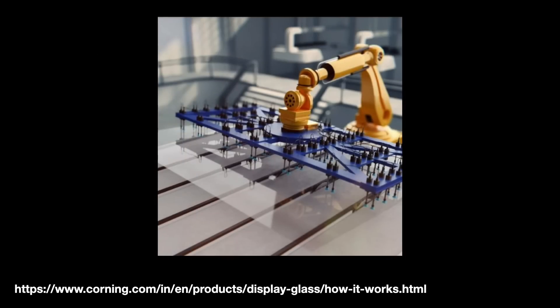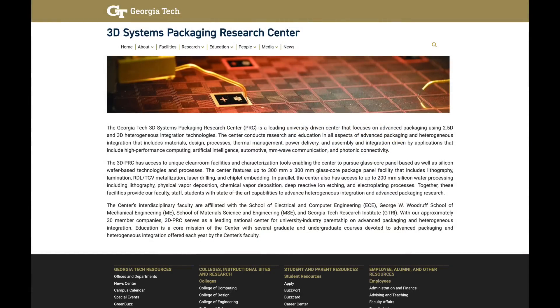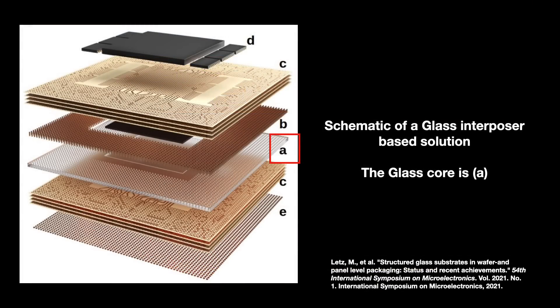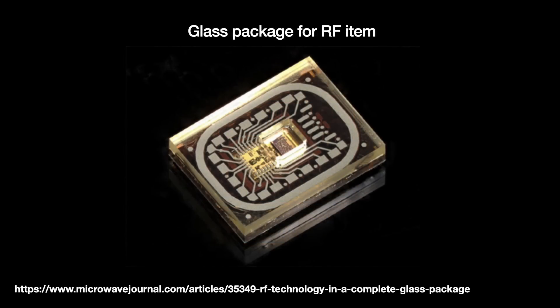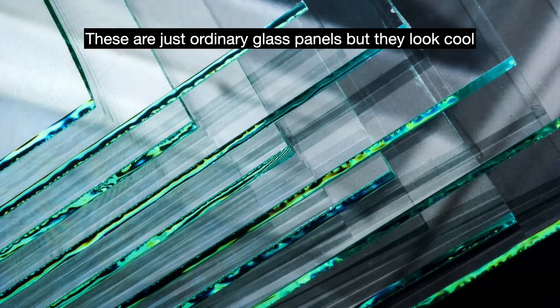With the LCD industry on the decline thanks to OLED's growing dominance, Corning has been doing R&D to see if their glass technologies can be applied to packaging. Since 2010, teams at the 3D Systems Packaging Research Center at Georgia Tech have been investigating glass interposers for high-performance computing. To make one, you start with a special glass panel core, drill thousands of through-glass vias (TGVs), fill them with copper, then laminate RDLs and patterns onto both sides. Glass is already used in a few applications like MEMS and RF — high compute would be like going to the major leagues. One key upside: we can adjust glass's CTE via its composition to better match it to the silicon die and substrate, reducing warpage.